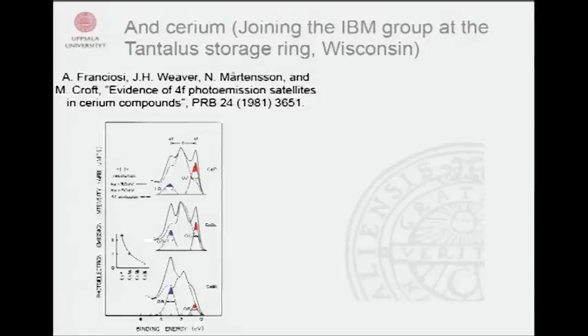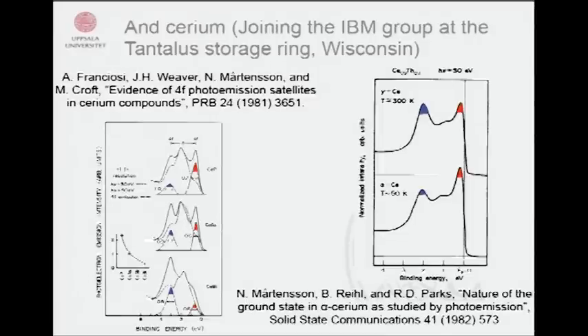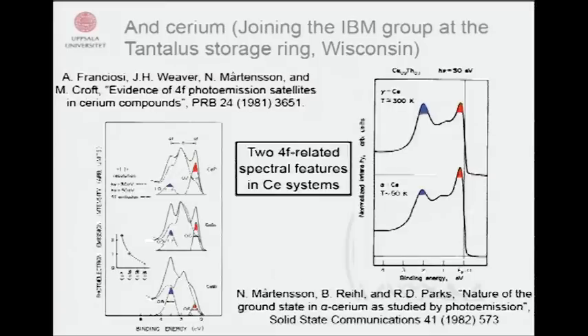where we could really see two photoemission features, one close to the Fermi level and one a few electron volts down. We also measured cerium thorium, because then we could have one sample and just heat it or cool it and look at the phase transition. These were of course impossible to get into Physical Review Letters, because it relied on comparisons of spectra at different photon energies, making subtractions, saying that this is 4f. And then the counter argument was that if we do it this way, then we get these double peaks for all cerium systems. And I guess that's exactly the point.